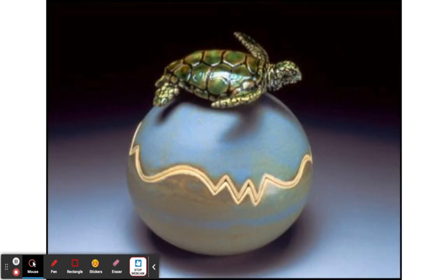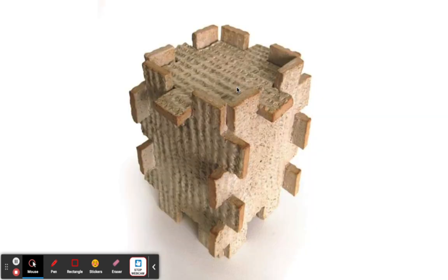I would just caution you with things like this. This turtle, they had to definitely poke holes into it. If your clay starts to get thicker than an inch, there's a higher probability for it to explode, and honestly, it's almost like half an inch. If it starts to get thicker than that, you need to poke some holes in it so the air can get out, okay? Things like this, okay? Really cool concept, really cool box.